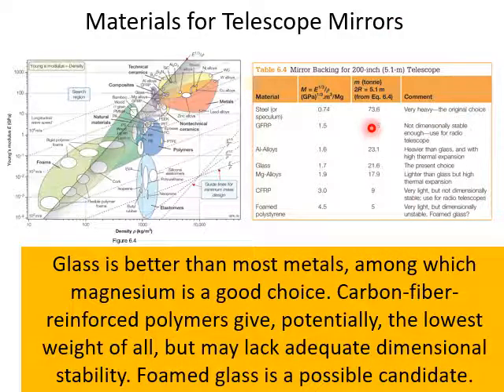So for example, the steel will be very heavy, which is the original choice, and then glass fiber reinforced plastic, which is not dimensionally stable enough, but you can use it for the radio telescope. Okay, and then you have aluminium alloys, which is heavier than glass and with high thermal expansion. Okay, you have already known that aluminium easily conducts thermal and also electrical. And then you have the glass, which is the present choice. And then you have the magnesium alloys, which should be lighter than glass but high thermal expansion, similar to aluminium alloys. And then you have a carbon fiber reinforced plastic, which is very light but not dimensionally stable, but it can be used for the radio telescope.